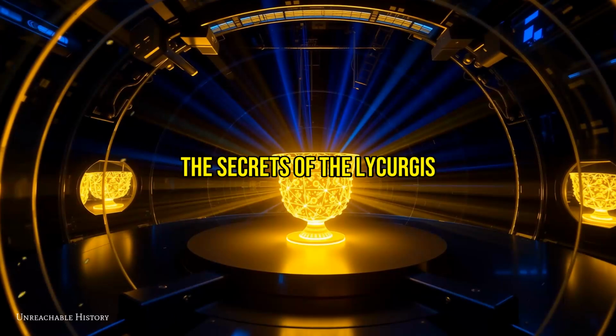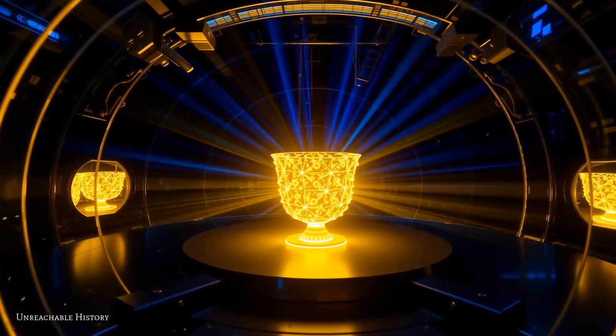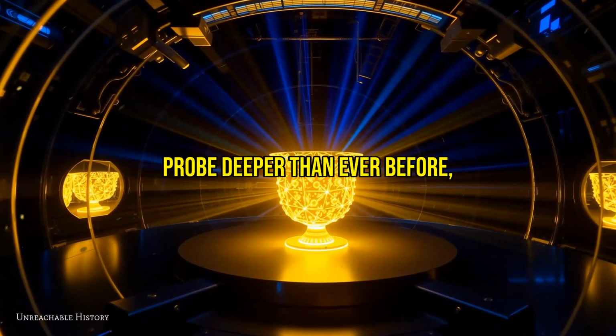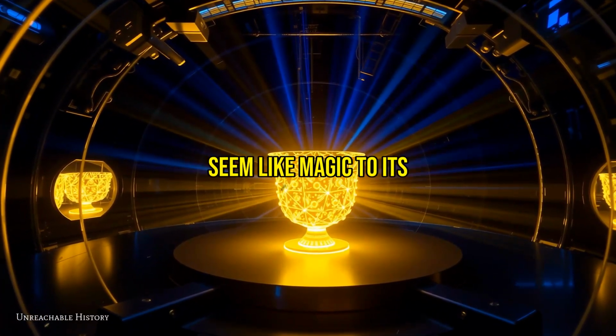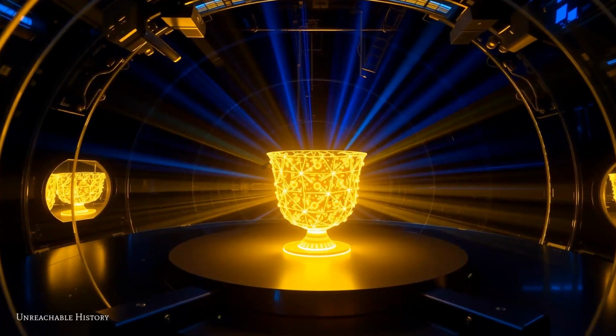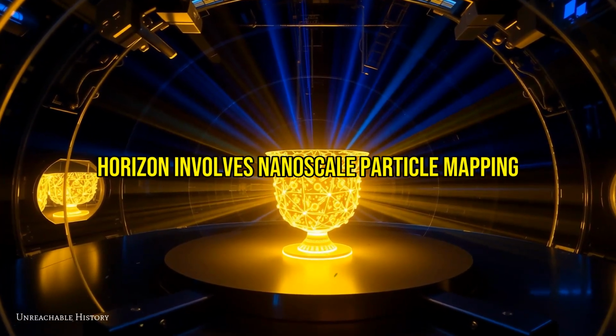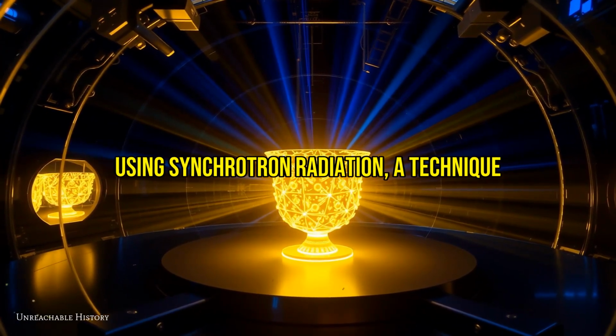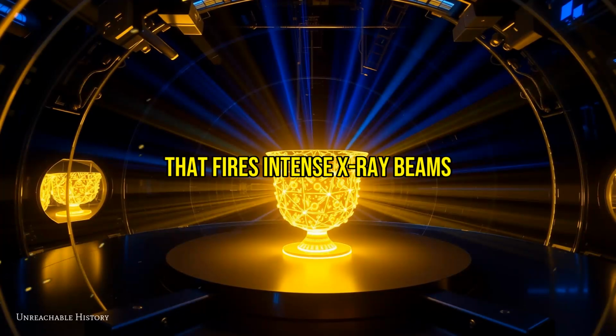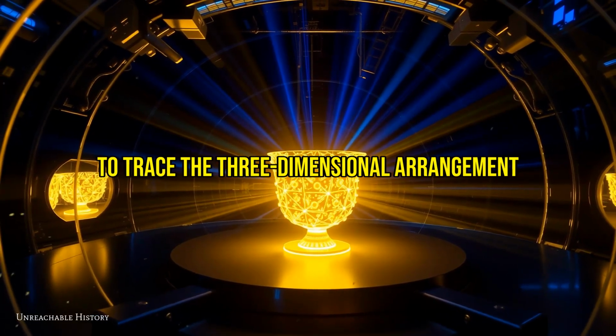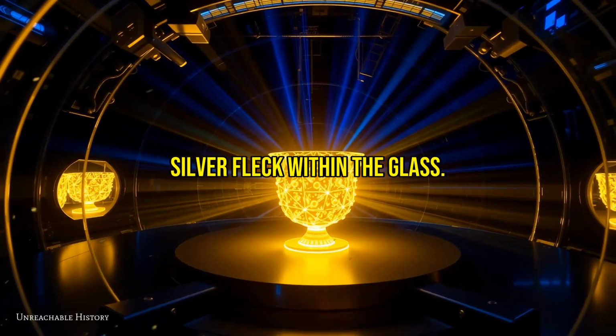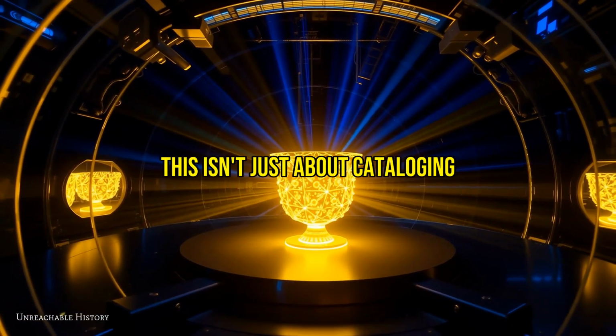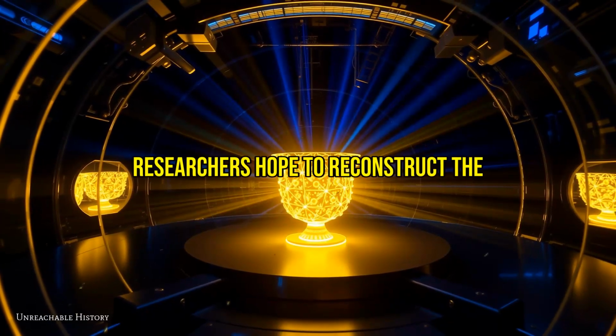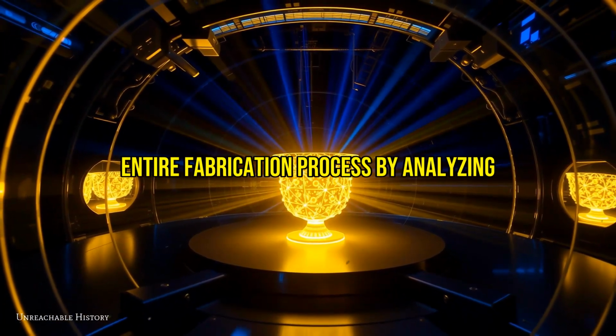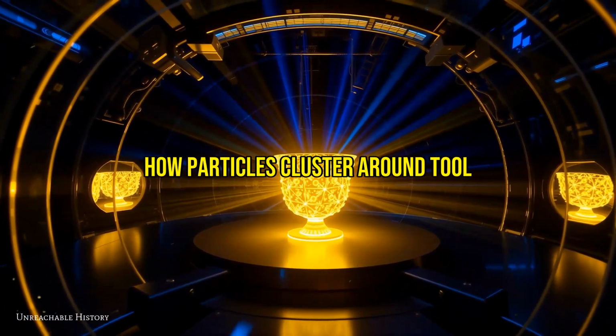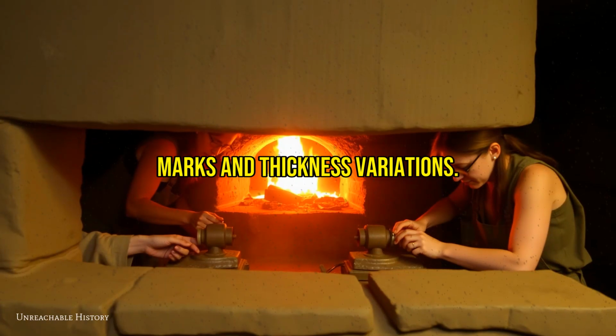The secrets of the Lycurgus Cup are far from fully unlocked. Scientists are now preparing to probe deeper than ever before, armed with tools that would seem like magic to its original creators. One groundbreaking study on the horizon involves nanoscale particle mapping using synchrotron radiation, a technique that fires intense X-ray beams to trace the three-dimensional arrangement of every single gold and silver fleck within the glass. This isn't just about cataloging nanoparticles. Researchers hope to reconstruct the entire fabrication process by analyzing how particles cluster around tool marks and thickness variations.